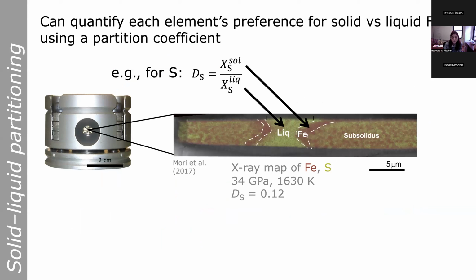So for example, if we're thinking about sulfur, the D for sulfur is just the mole fraction of sulfur in the solid divided by the mole fraction of sulfur in the liquid. You can do this with a variety of experimental or computational methods. This is an example from Mori et al. 2017. For example, you can use a diamond anvil cell, subject your sample to high pressures and temperatures to partially melt it, bring it back down, recover it. So here, this is an image of a cross-section through their recovered sample that was from 34 GPa and 1630 Kelvin. And then they did this X-ray mapping of the sample.